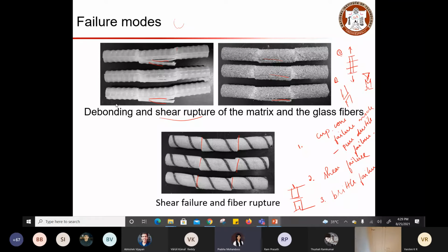So when the bond resin is not adequate or it is done poorly, then you observe such type of debonded matrix, or you can see a lot of fibers coming out from the FRP composites as it is not able to take the load. So in such cases, you will be observing debonding and shear failure of the matrix and glass fibers. So if the resin and fiber matrix is good under the load, then you observe such type of shear failure, and after a certain loading point, it cannot take further load, so your fiber gets ruptured into pieces.